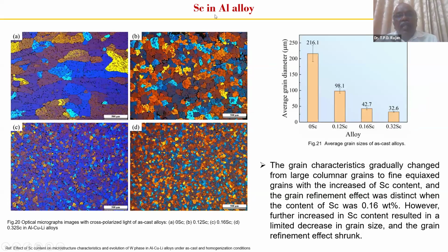And what happens when the scandium is added? So this is a normal microstructure of an aluminum copper lithium alloy. And once we add the scandium, the A structure is without scandium, and the B is 0.12% scandium, 0.16 and 0.32% scandium. So you can very clearly see that the grain size is getting reduced. So one of the ways to enhance the strengthening is by reducing the grain size. I think you remember in the first slides which I mentioned, finer the grain size, enhanced the properties.